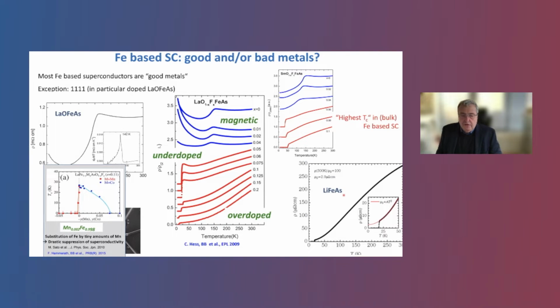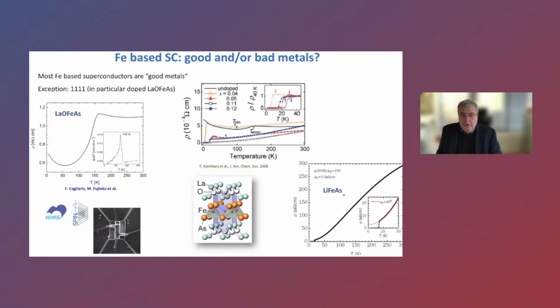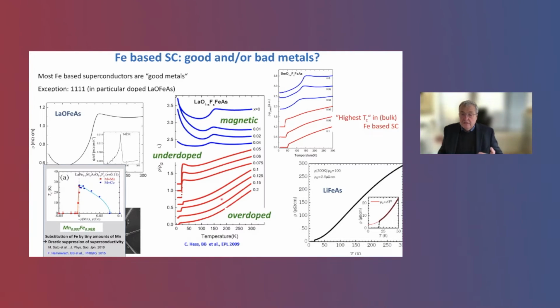If you have a look on the structure, of course, there is a difference. We have these iron arsenide layers embedded between lanthanum oxide layers. This makes the system probably much more two-dimensional. It's also, from chemistry, completely different. It's not an intermetallic compound. It also makes it much more difficult to synthesize the crystals. Still, it is a system showing the highest TC.